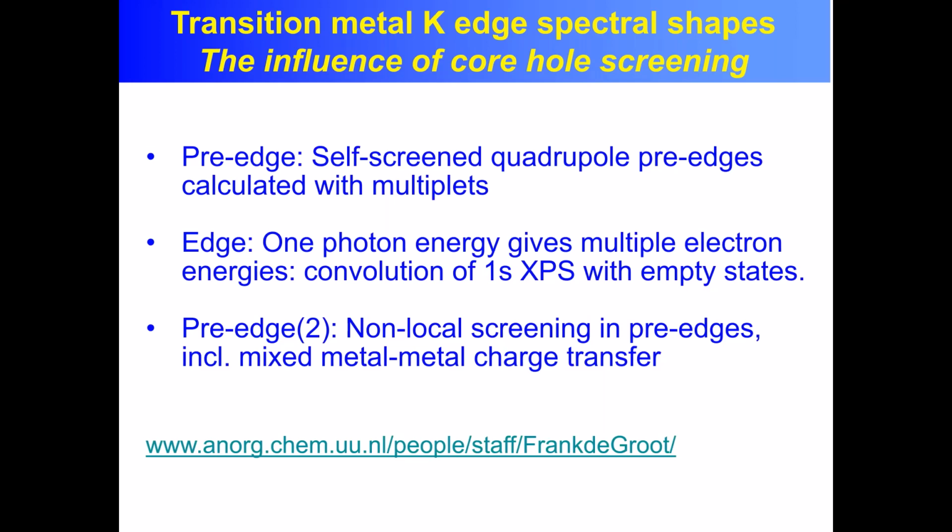Frank, thanks for this nice talk. In the late 80s, there was work on lithium-doped nickel oxide, where as lithium is put into nickel oxide, most of the charge compensation is supposed to take place on the oxygen, right? It's more or less like a negative charge transfer insulator. But if you look at the K edge of nickel oxide, you really don't see a big non-local interaction.